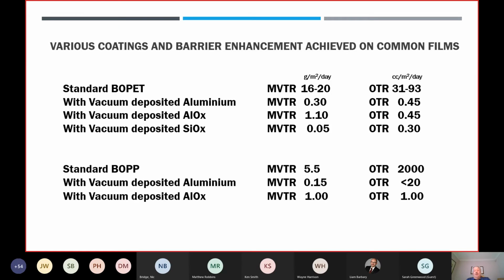Standard BOPP with vacuum deposited aluminium, you know, big improvement in moisture barrier from 5.5 to 0.15, but polypropylene inherently does not have an oxygen barrier, so by putting the aluminium on there, you're taking it down to less than 20. And with vacuum deposited AlOx, you also see a massive improvement.